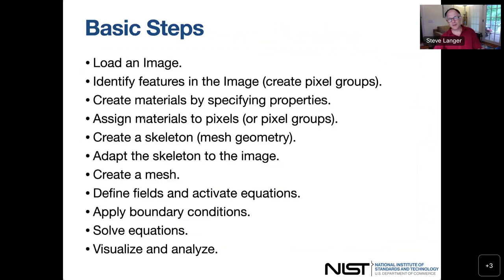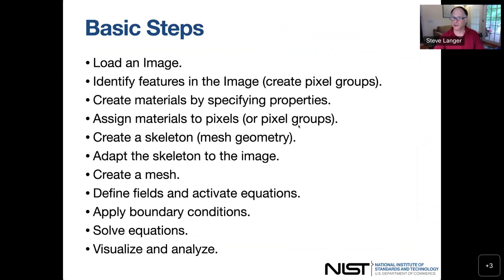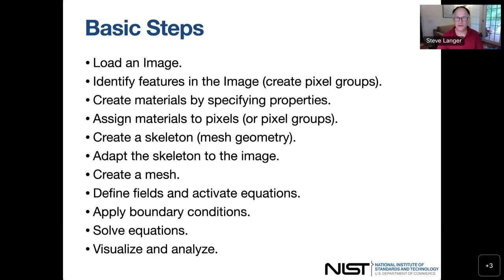From a skeleton, you add on the mathematics and the physics, and that gives you a real finite element mesh. On that mesh, you can compute a solution to the problems you're interested in. The basic steps are: create a microstructure by loading an image, identify the features in the image, create materials by specifying the properties, assign materials to pixels or pixel groups, create and adapt the skeleton to the image, create a mesh, define fields and activate equations, apply boundary conditions, solve the equations, and visualize and analyze the results.